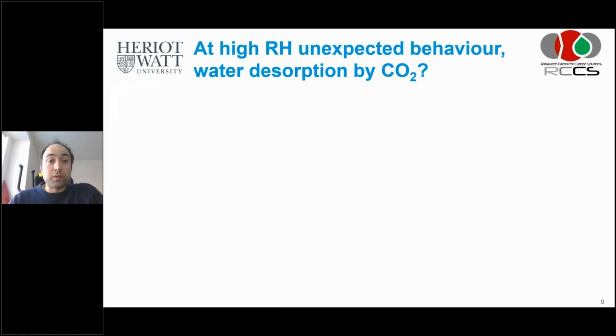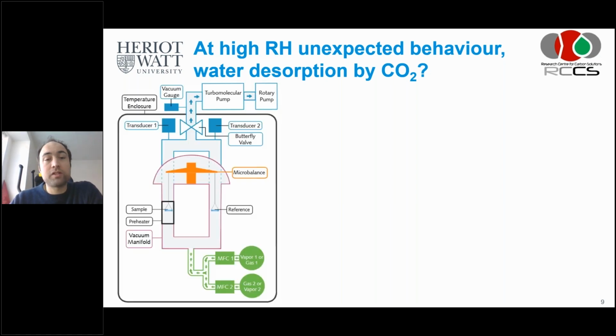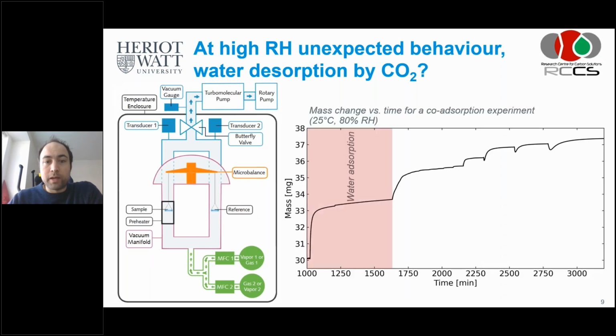Now I already told you that this approach, this method works if water is not desorbed by the presence of CO2. And that was perfectly fine at a relative humidity of about 60% or lower. But we also saw unexpected behavior when we went to very high relative humidity, so 80% and above. And what you see then is that actually